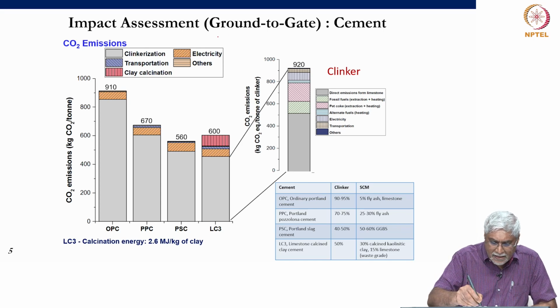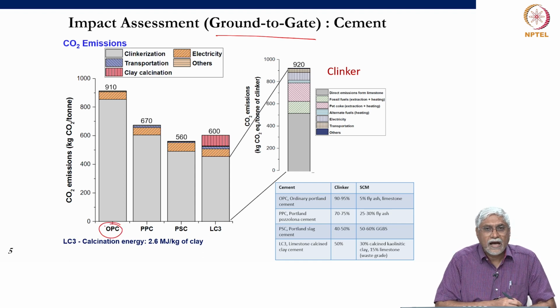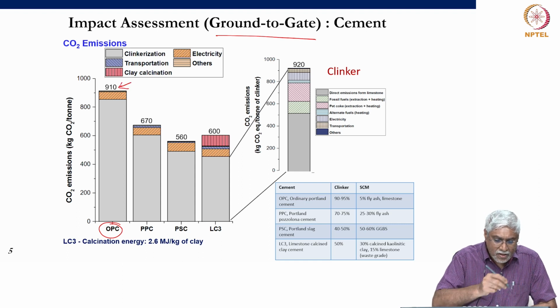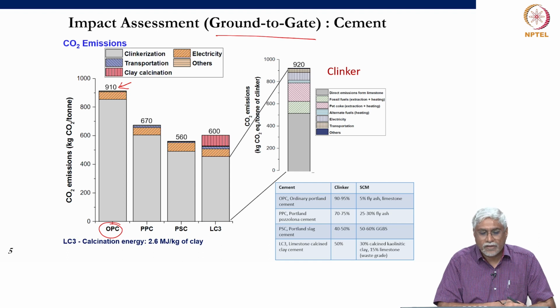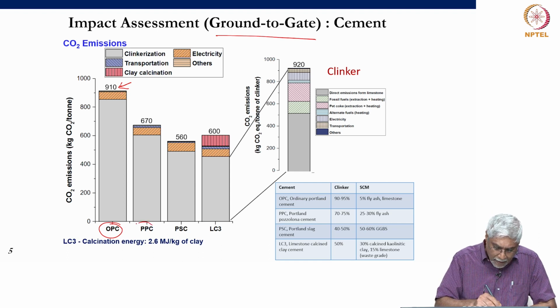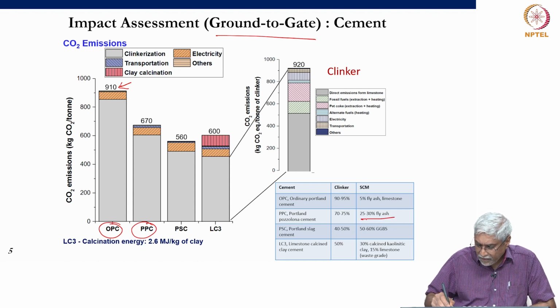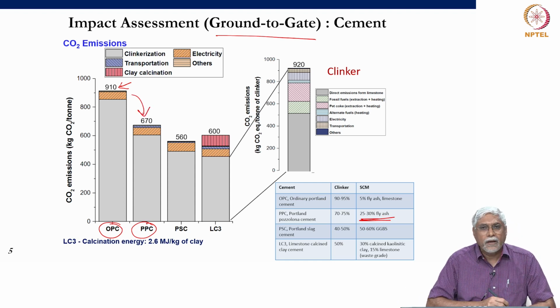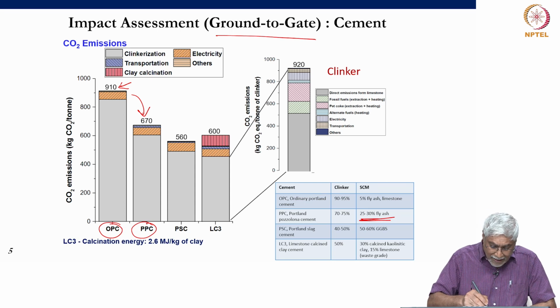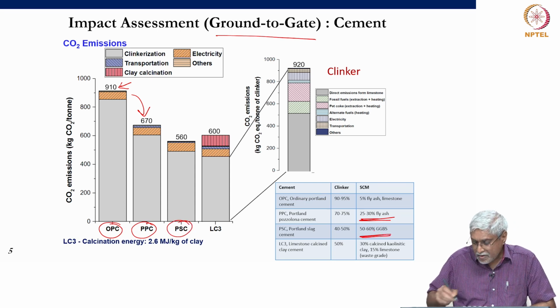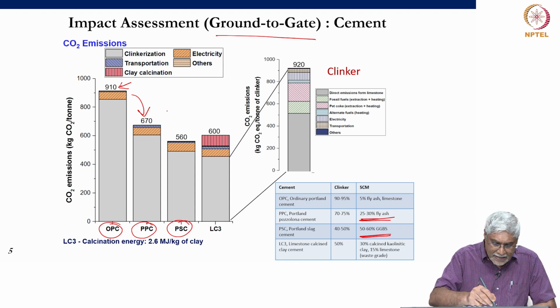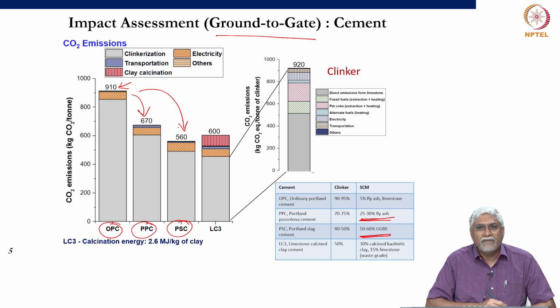So, in the ground to gate system, say in this particular plant, if I am going to make a ton of ordinary Portland cement, I would have more than 900 kg of CO2 emitted for every ton of ordinary Portland cement. Suppose it is Portland pozzolana cement, where I have a lot of fly ash, 25 to 30% of fly ash. The CO2 emission comes down by a substantial amount from 900 to less than 700. In Portland slag cement, I have more substitution of the clinker, and then you see that this is even better. It comes down to about 550 kg of CO2.